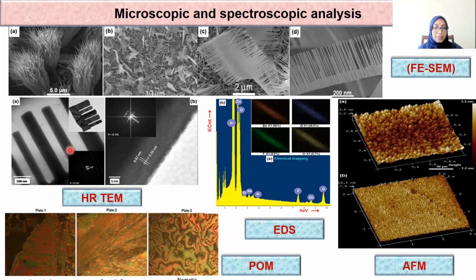Then the high resolution TEM, that is the HRTEM, together with the selected area diffraction, that is the SAED pattern, is performed to examine the crystalline structure, size and shape of the synthesized zinc oxide nanocomb. These images were critically analyzed to describe the atomic structure. And they also demonstrate that the nanocomb teeth are associated along one side of the ribbon-like stem. HRTEM images and the SAED pattern provide an important study of the crystal structure of the zinc oxide nanocomb.